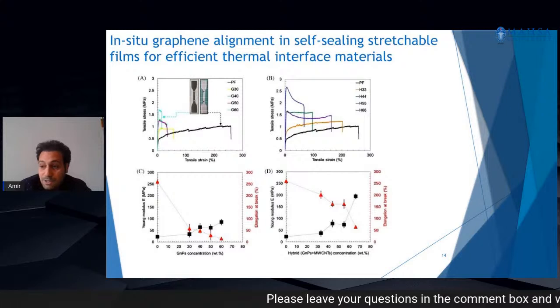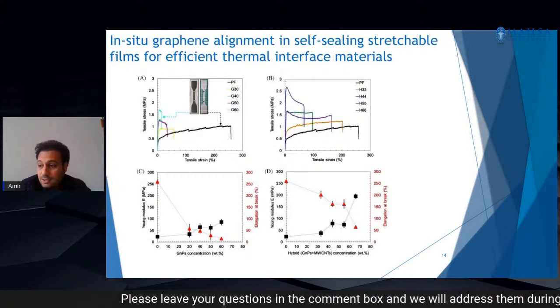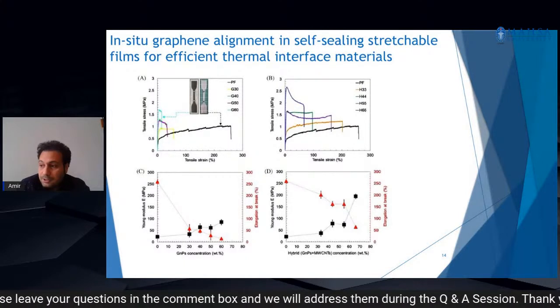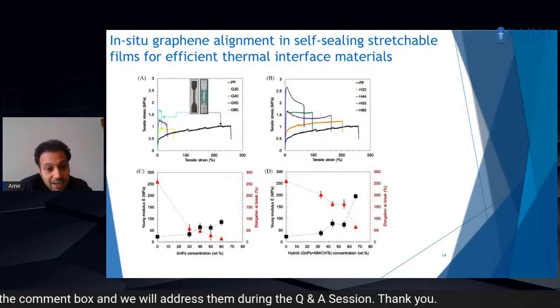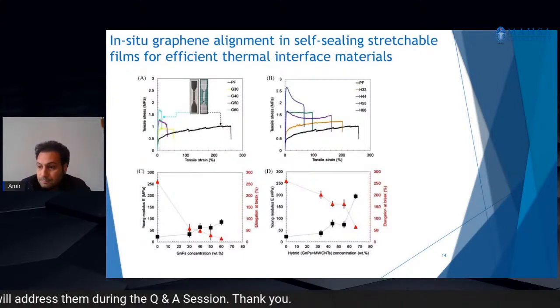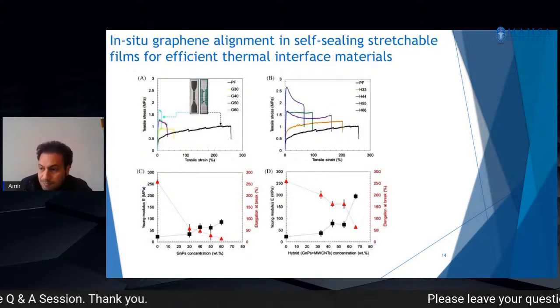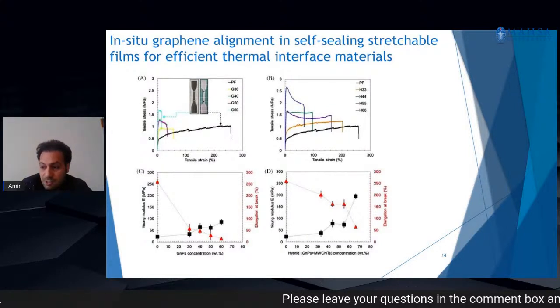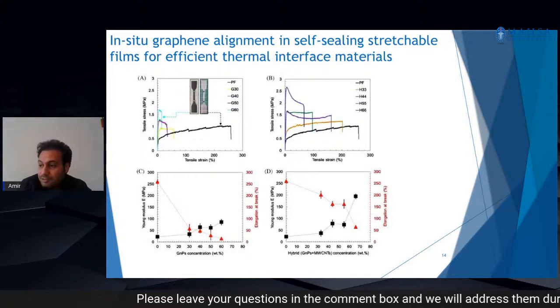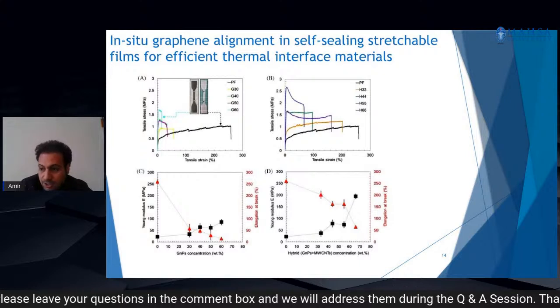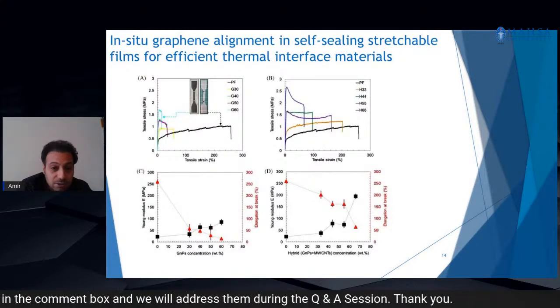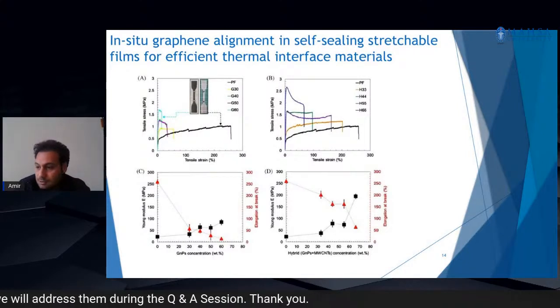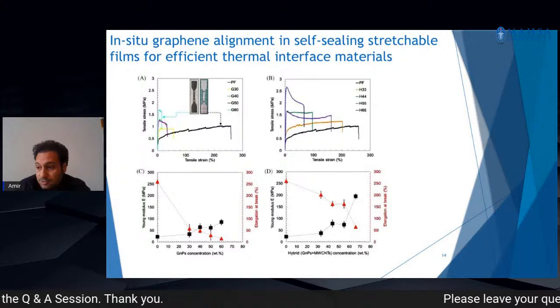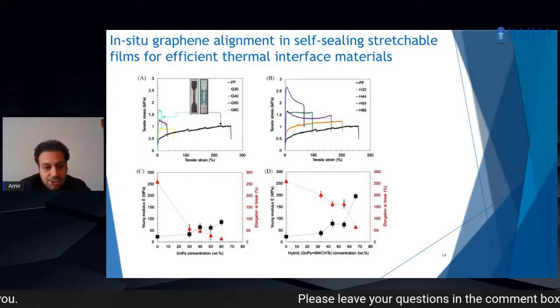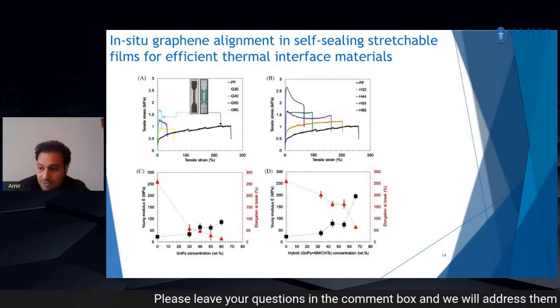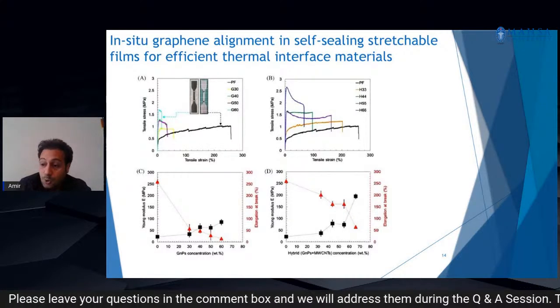The mechanical properties of the nanocomposite pads after hot pressing were measured to obtain elastic modulus and elongation at break values. The unfilled PF sample is a highly elastomeric soft polymer with an elongation at break value of 260 percentage and elastic modulus of about 23 megapascal. Adding 30% of the GnPs reduced the elongation at break value to 60% with a slight increase in elastic or Young's modulus.